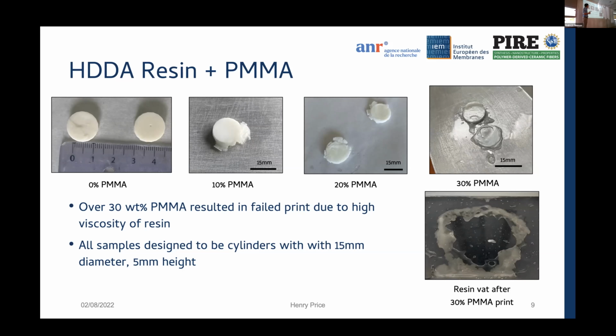One of the most important results is that over 30% PMMA, the prints consistently were unsuccessful. This was because of the increased viscosity of the resin itself, which the increased amount of beads made possible. As you can see, at 30% PMMA, these prints are not a full height. There are large cavities compared to a successful print, which would be a full height cylinder. I was printing cylinders with a 15 millimeter diameter and a 5 millimeter height.